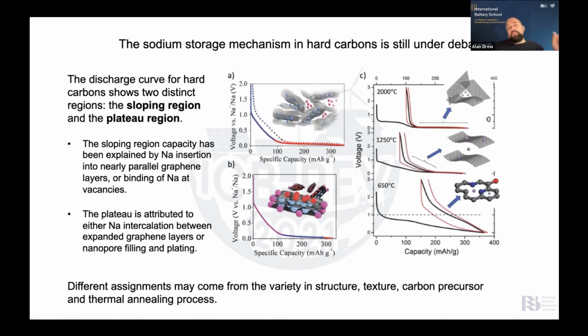So the mechanism of storage in sodium-ion batteries is still under debate. It is believed that this region here, this plateau region here, corresponds to sodium that's sitting in the pores in here. Okay, and then this is intercalation between these expanded graphene layers in these pores. And then in this region here, where you see the slope, it is believed that it sits within nearly parallel graphene layers, or binding at vacancies. Okay, that's what's believed.